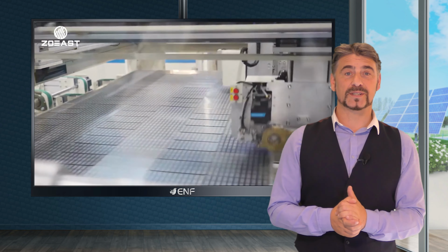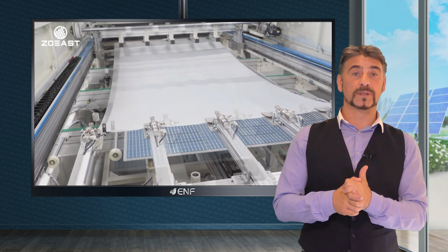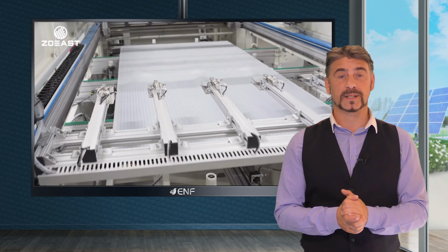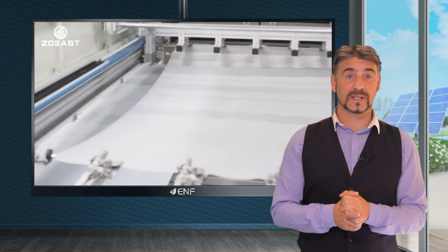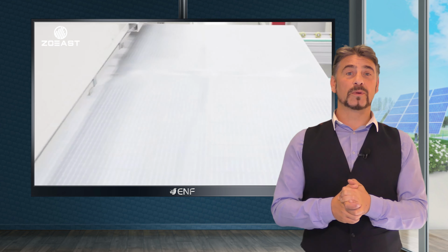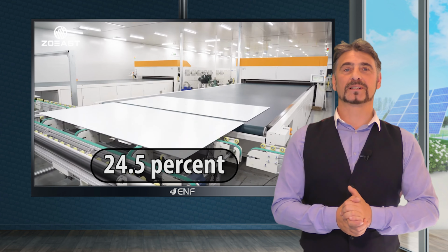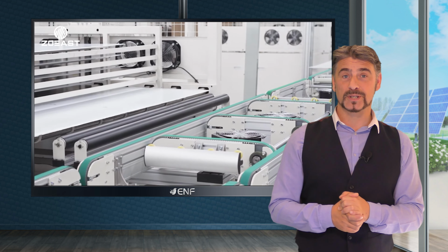Other notable features of this cell's bus bar include silver plating that helps improve current conductivity while reducing oxidation at the same time, as well as blue silicon nitride with an anti-reflection coating, which reduces optical losses and enhances surface passivation, leading to a high efficiency rating of 24.5%. All of these allow our product to have outstanding power output even in low light or high temperature conditions.